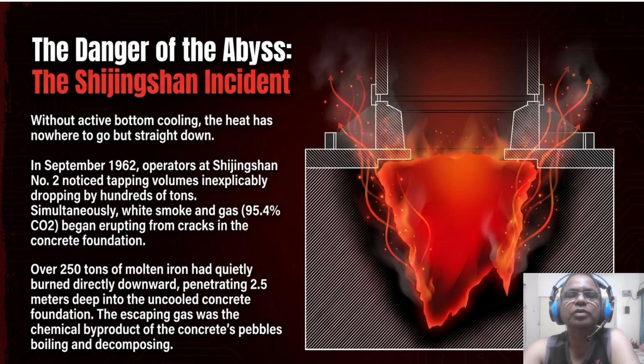Without active bottom cooling, the heat has nowhere to go but straight down. In September 1962, operators noticed tapping volume inexplicably dropping by hundreds of tons. Simultaneously, white smoke, which was 95.4% CO2, began erupting from cracks in the concrete foundation. Over 250 tons of molten iron had quietly burned directly downward, penetrating 2.5 meters into the uncooled concrete.